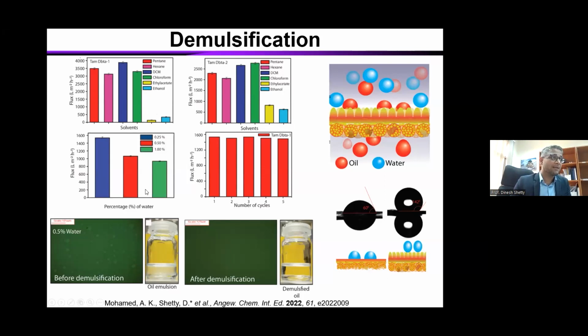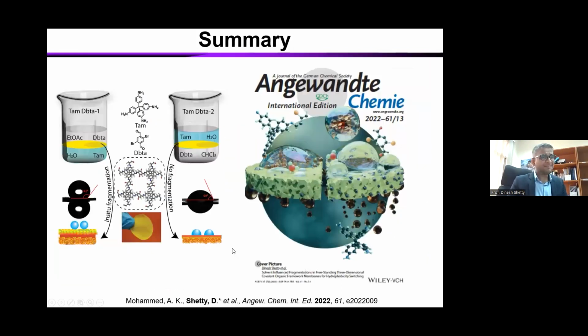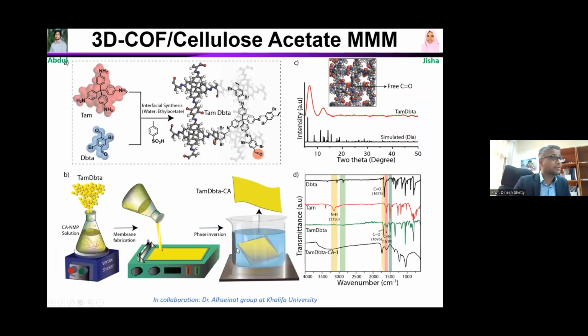And then what we did, demulsification application by varying the amount of water. In this case, when you have a mixture, water is completely repelled from the membrane. But we have to remove that water in between, otherwise it is blocking the surface of this membrane. That's the reason you end up getting a decreasing flux over time. But if you continuously remove this water, then obviously flux is maintained, as you can see here with the different number of cycles. And these are the optical microscopic images. It clearly shows when you treat this with the membrane, you have no water droplets in the mixture. This was the first story. We were very excited. We were able to publish it in 2022.